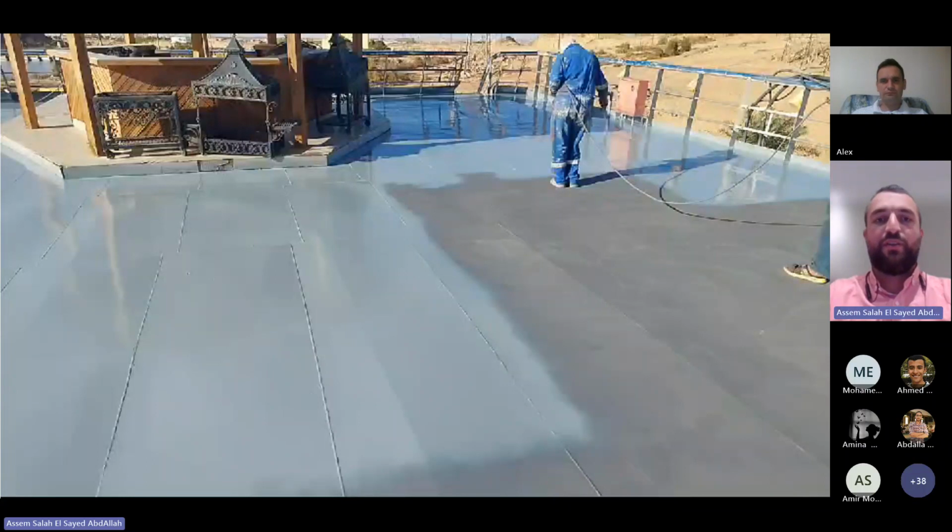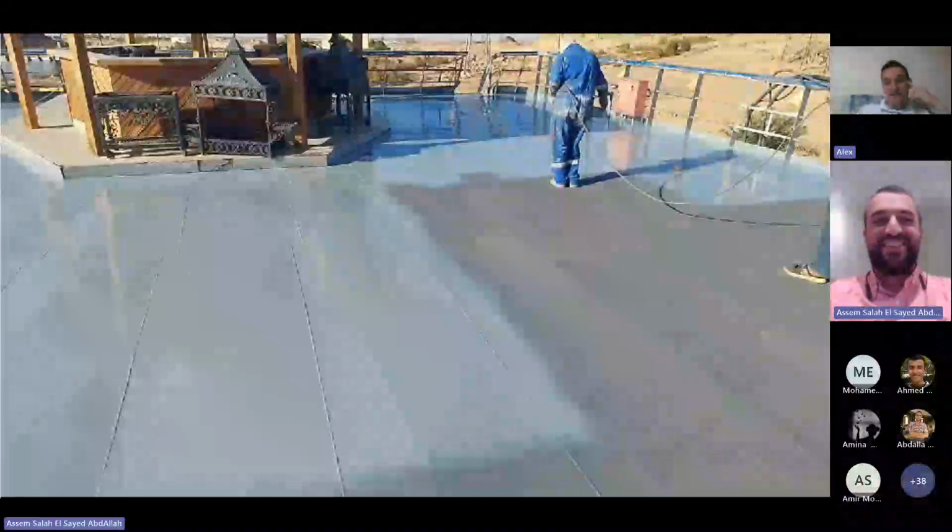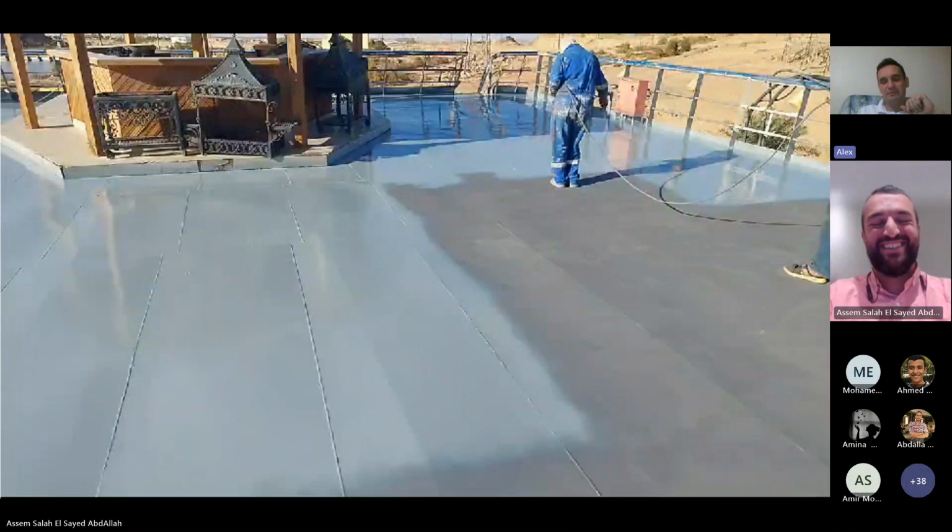Okay. And by the way, this is from our recent project with Mr. Alex, this trip. Yes, talking about this recent project in Egypt, in Aswan, which is located in one of the driest cities of the world. We must mention that there's almost no electrolyte, and I spent a week there, for example, and I saw a lot of bare steel absolutely uncoated, exposed to the sun, and it had no visible corrosion at all. I was amazed.